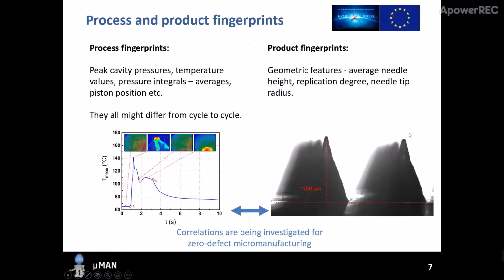In our case study, this is the average needle height from one microneedle part, or one microneedle array. It is the average needle height from 36 needles, which is our product fingerprint. It could also be defined as the replication degree or needle tip radius, but to simplify the problem, we use the average needle height from one cycle or one part. At the end, we would like to see correlations between process fingerprints and product fingerprints, and whether there are any meaningful relationships between these process features, inline process data, and product fingerprints, which is the geometric outcome of our products, which could lead us to zero defect micromanufacturing.